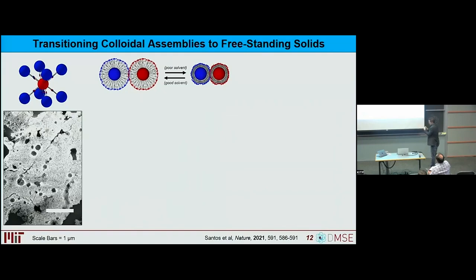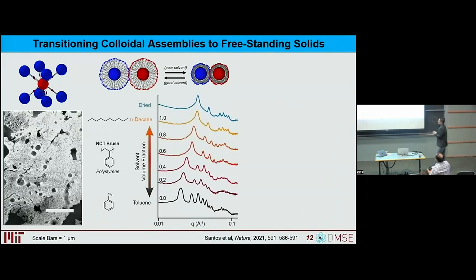Everything should condense down to one another, and now when we dry them out, we should be able to dry them without capillary forces pulling everything apart. Sure enough, this is exactly what we see. If we assemble our BCC type lattices in toluene, we gradually transition them to n-decane.